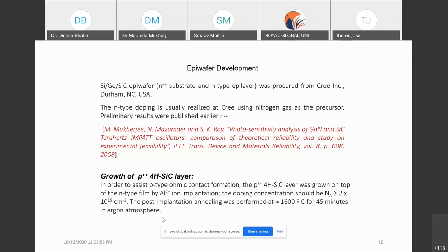Durham, USA. And we have chosen the N++ substrate. The background of choosing it is that in the case of electrons, the mobility will be higher for silicon carbide. And when the mobility is higher, it is expected that the parasitic resistance will be lower. So that is why, instead of a P++ substrate, which is also not much available in the market, we have